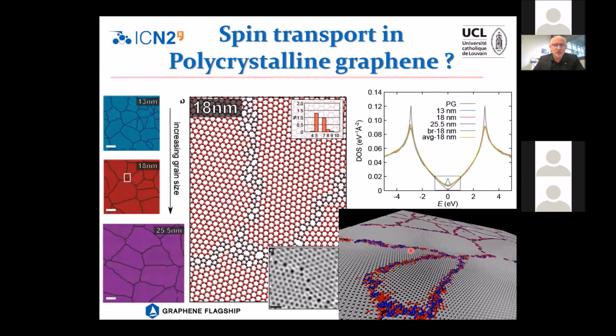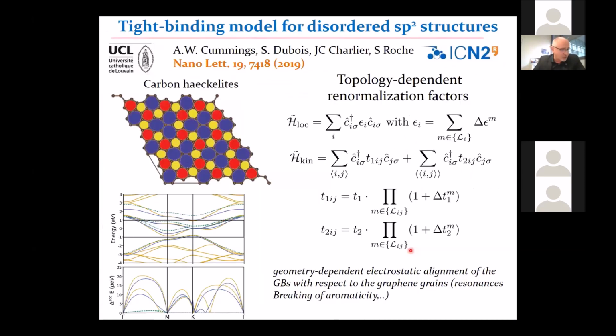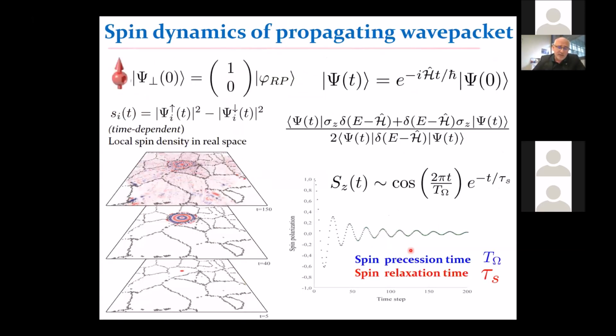One was to try to anticipate by developing modeling on that. So we elaborated a realistic model of polycrystalline graphene. We worked also on modeling how all this disordered structure will impact the energetics, including the spin orbit coupling impact from the substrate. And we also developed a methodology to track the spin dynamics of electrons moving in these materials.